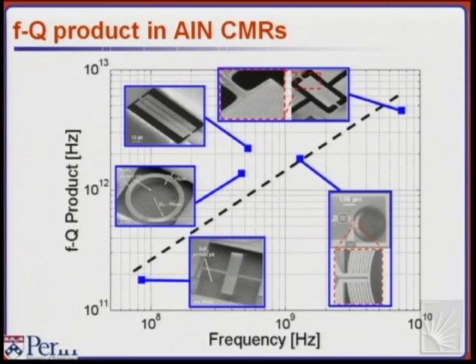It's probably a more important figure of merit. But anyway, the FQ product is an important one, and you can see how we achieved the highest FQ product at higher frequency. We didn't effectively increase the Q, but we sort of maintained the same Q almost even at high frequency. So it's interesting to see how making it smaller doesn't really hinder us.